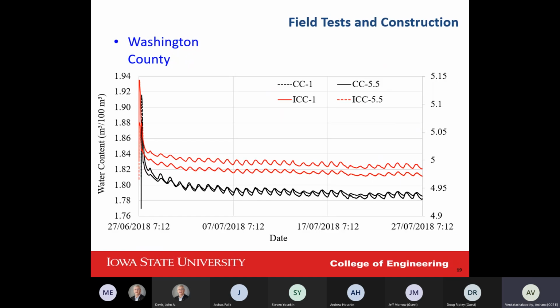But more important than that, the water content or moisture. Well, they're different, but we could measure the water content with the 5TE sensors. So the water content in internal curing is the red lines, and in control concrete or the normal slab is the black one. So we can see the water content stays much higher in the internal curing versus the normal concrete. And why is that happening?